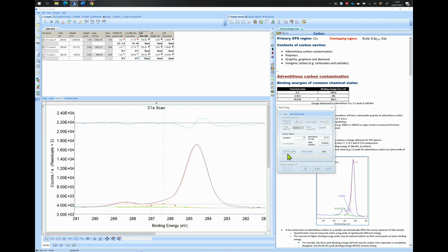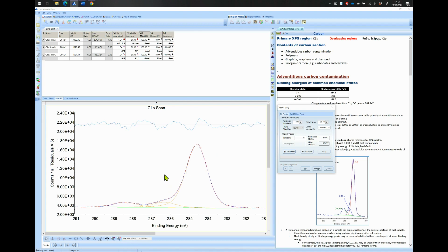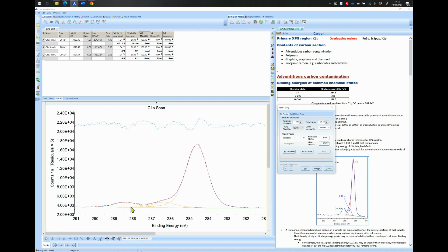The result is better. The width of the peaks is close to 1.3 eV and the LG ratio also close to 20% but not quite. For most cases, the C single bond C should be around 284.8 eV and the C single bond O should be close to 286 eV. You will also often get a OC double bond O around 288.5 eV.